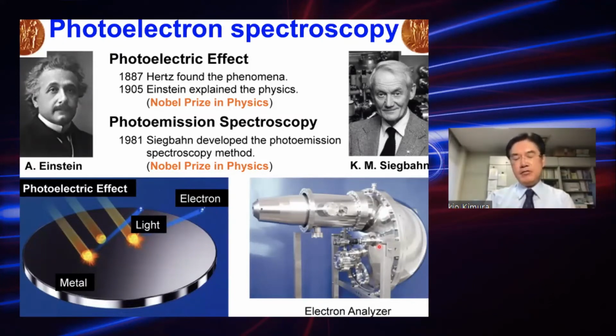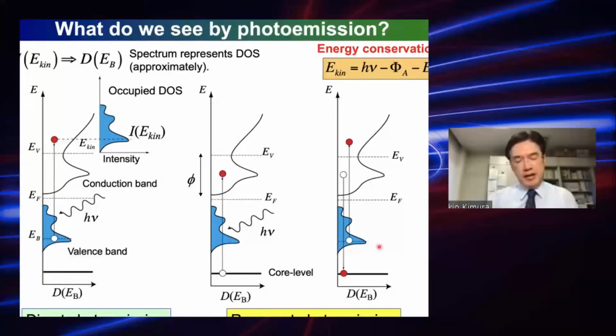So it may be important to look at the electronic structure directly and experimentally, in order to develop future functional materials with improved functionalities. One of the experimental tools which may be good for this is photoelectron spectroscopy. As you can see here, irradiated by synchrotron radiation, you can count the number of photoelectrons as a function of kinetic energy, sometimes as a function of emission angle. So you get approximately the density of states below the Fermi energy, according to the energy conservation rule.